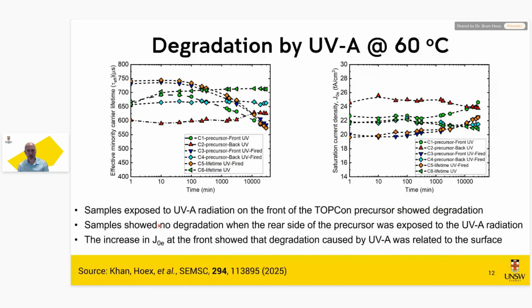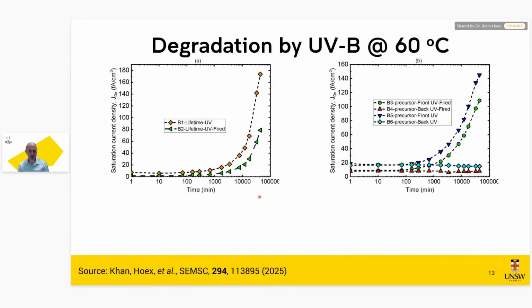And we could attribute the whole increase in recombination to an increase in surface recombination. So no bulk defects in this case. If we then look at UVB exposure at the same temperature, in this case we just plot the saturation current density, so that's the recombination current. We see a massive increase. And we see a significant difference between the fired and the unfired sample. The fired sample is more stable than the unfired sample. And this is something we will come back to. So this is one piece of the puzzle in understanding the mechanism and also how to address UVID